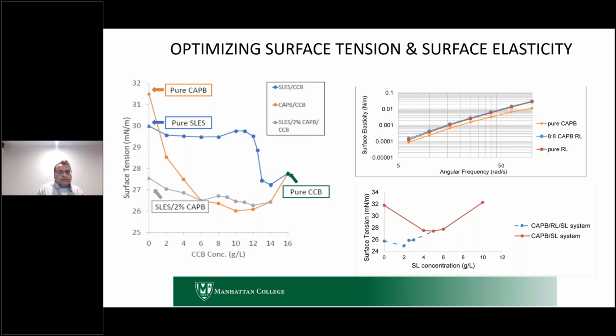that basically we start to replace traditional surfactants with CCB, which is your rhamnolipid. And we start with a pure Cap B or a pure SLES, and with a pure SLES Cap B, and we start introducing more and more of this rhamnolipid. And what is quite interesting is that especially with the Cap B system, the cocoamidopropyl betaine system, you get to a surface tension reduction